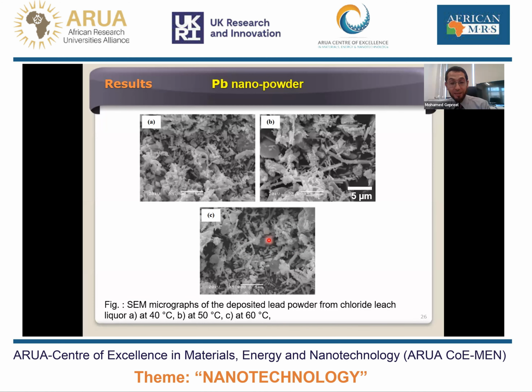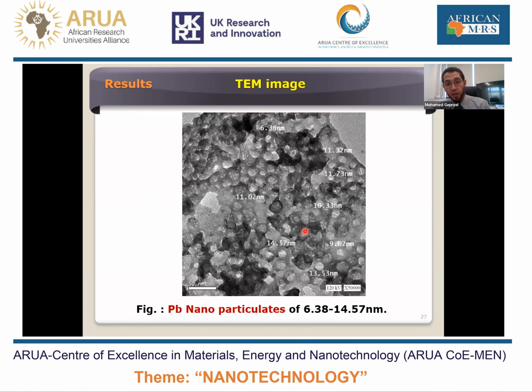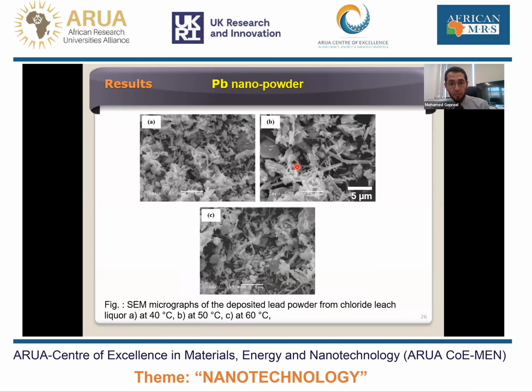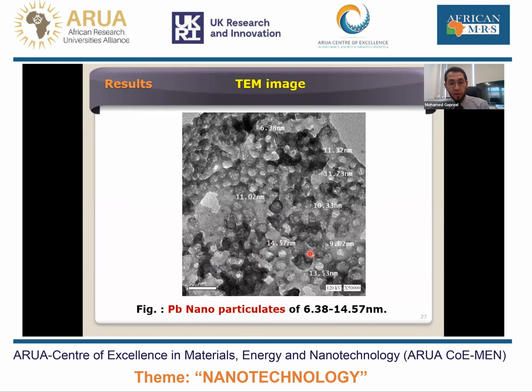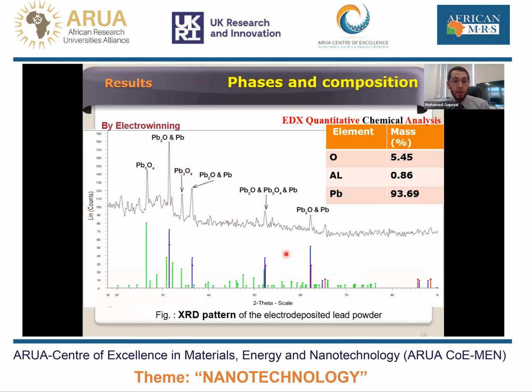Anyway, at high magnification by TEM, we can see that this type of powder is agglomerates of very fine nanoparticles, as we can see here. At this magnification, this is 50 nanometers. So we have a lead particle size range of 6 to 14 nanometers in agglomerates, with some shells of other material itself. Actually, we investigated this deeply, and we found that the process gives such a nanopowder, but this nanopowder is not pure lead.